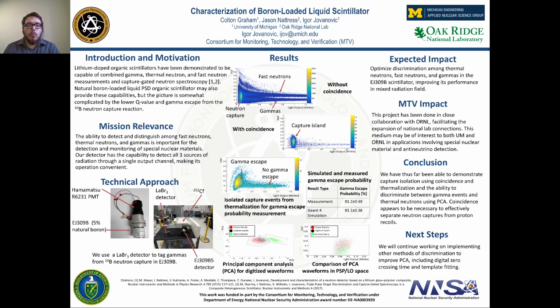One of the theories for why the pulse shape parameter for capture events is so suppressed is the energy deposition from this photon. So we used this measurement to make a determination of the probability of that gamma to escape with all of its energy, which you can see reported here, alongside that value obtained through GEANT simulation. And you can see in both cases, the gamma escape probability is in excess of 80%, suggesting that an alternative explanation is needed.